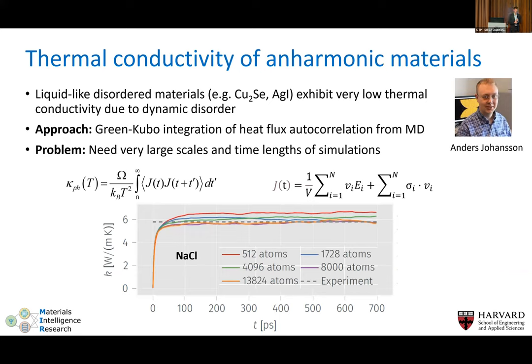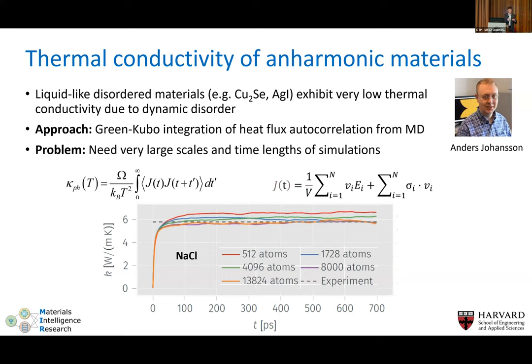You also get good vibrational properties and can compute thermal conductivity. For crystalline materials, the Phoebe code — which we're developing — enables Boltzmann transport for electrons and phonons, achieving quite reliable thermal conductivity predictions compared to experiment. For glasses, liquids, or non-periodic systems, thermal conductivity can be computed using the Green-Kubo formalism, calculating the autocorrelation function of heat flux using local energies and stresses. These are very large, long simulations for which machine learning potentials are the appropriate method, as demonstrated for sodium chloride, a very anharmonic crystal.